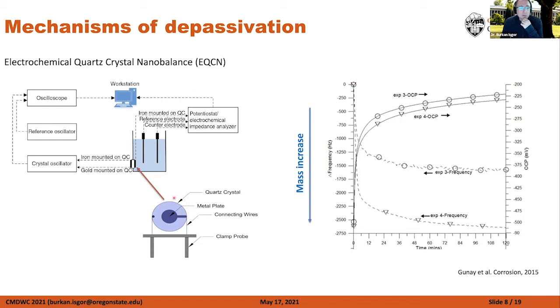Basically, a quartz crystal is a piezoelectric material. When you pass an AC current through it, it starts vibrating at a certain frequency. And if you change the mass of that crystal, you change the vibration frequency, which means that the vibration frequency can be correlated to the mass change of the material. This is a very useful tool because you can do this in nanograms, in very, very small quantities.